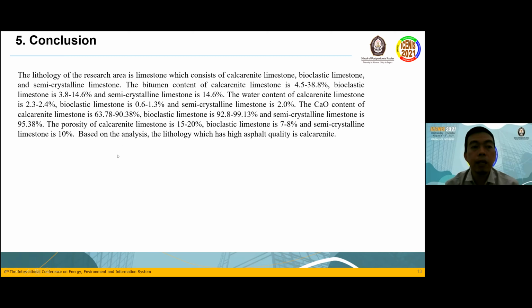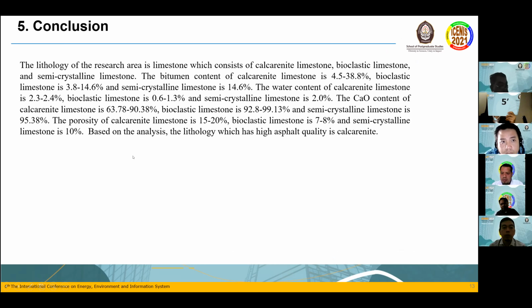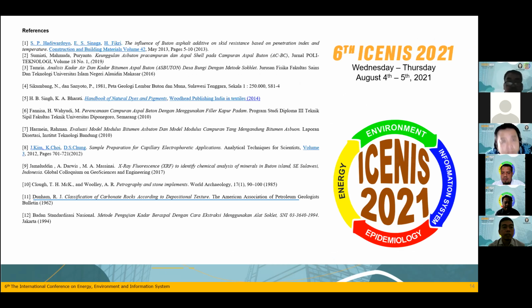The CaO content of calcarenite limestone is 63.78 to 90.38%. Bioclastic limestone is 92.8 to 99.13%, and semi-crystalline limestone is 95.38%. The porosity of calcarenite limestone is 15 to 20%. Bioclastic limestone is 7 to 8%, and semi-crystalline limestone is 10%. Based on the analysis, the lithology which has high asphalt quality is calcarenite limestone. And these are the references we used in this research, and thank you.